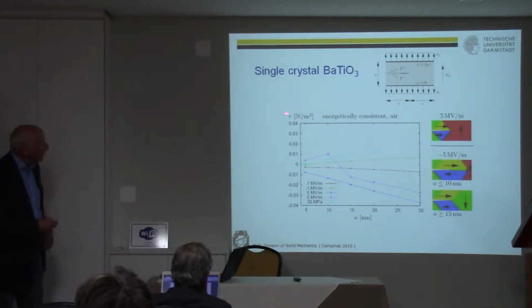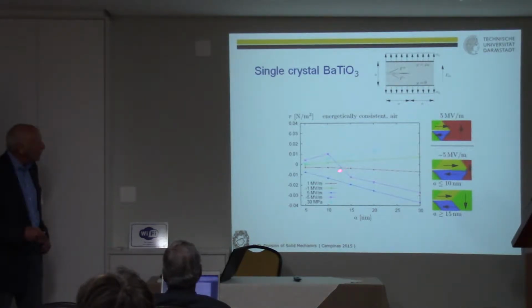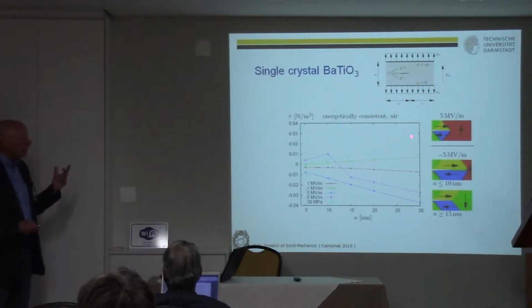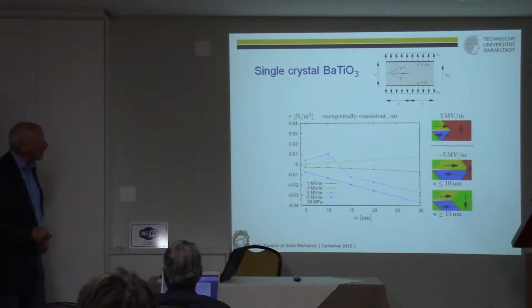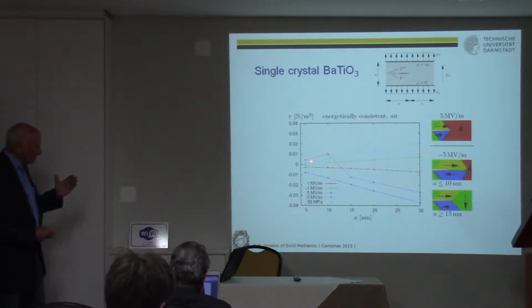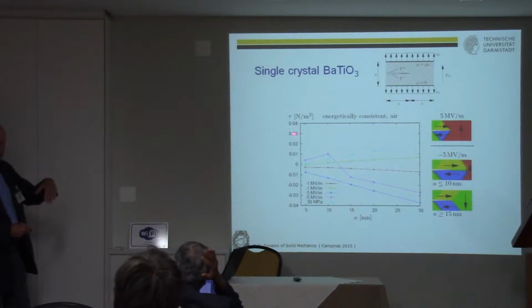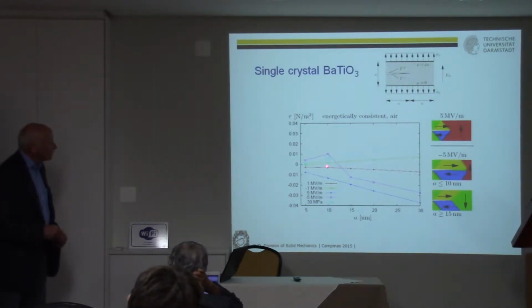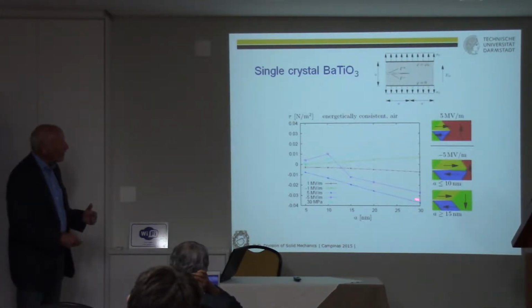Here is a driving force again. It's another notation here, and here you see the geometry parameter A. And you see that the driving force now depends strongly on A, the size. You have a size problem here. This here is not a mistake. This curve shows that the microstructure at the crack tip changes here. The one system of domain walls is no longer stable and it changes to another polarization pattern. And this gives rise then to this jump in this curve. Okay.